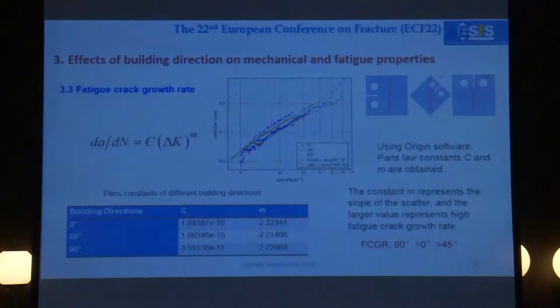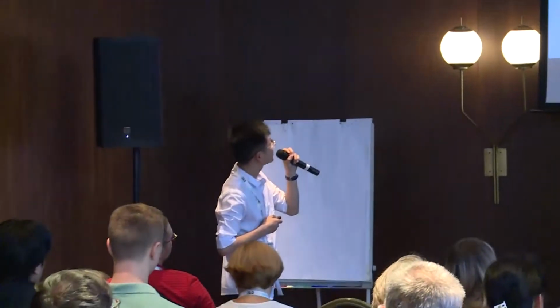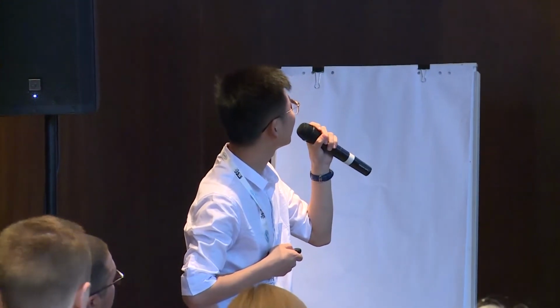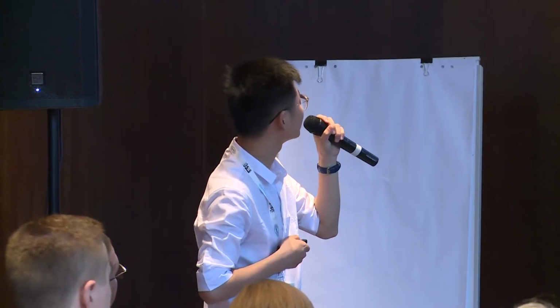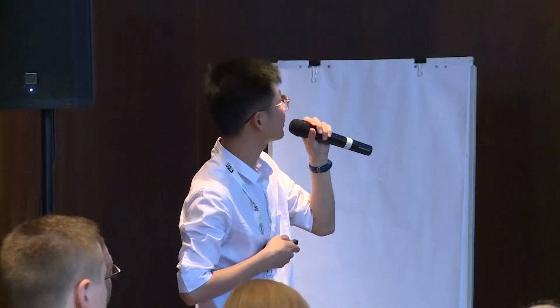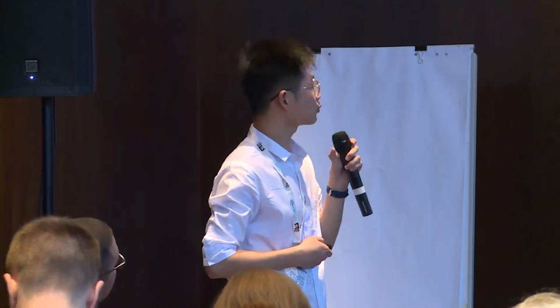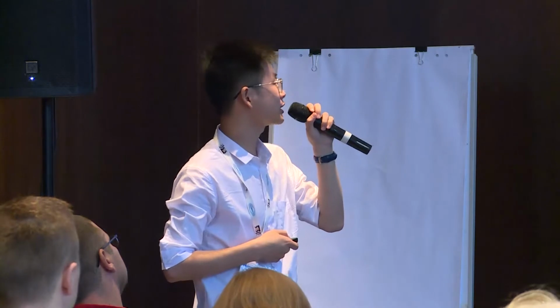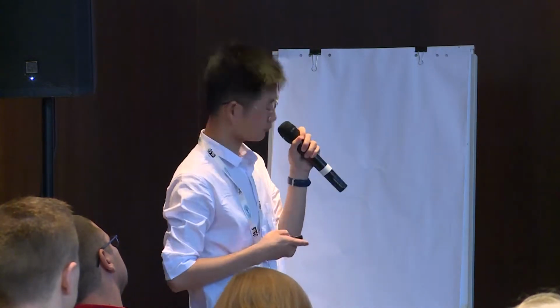And then using Origin software, the Paris law constants C and m are obtained in this table. The constant m represents the slope of the curve, as a large value represents a high fatigue crack growth rate. In this picture, the 45-degree samples have a small slope, and the m value of 45-degree samples is lowest. So we can draw the conclusion that the 45-degree samples have the lowest FCGR.